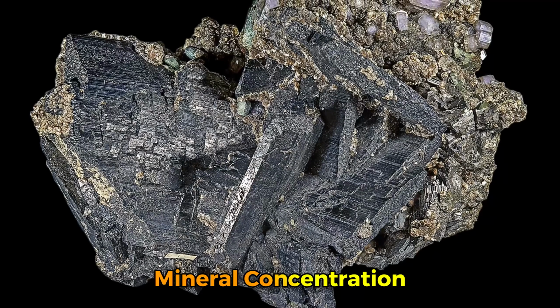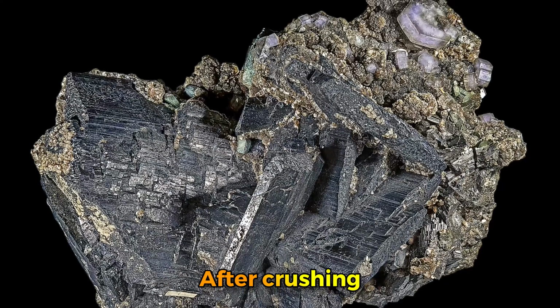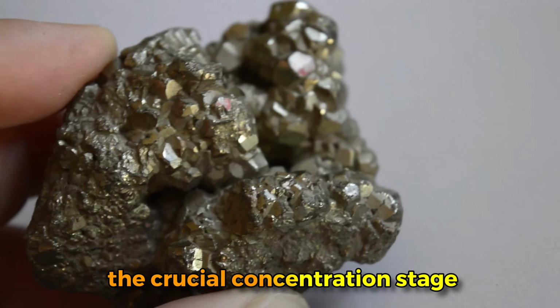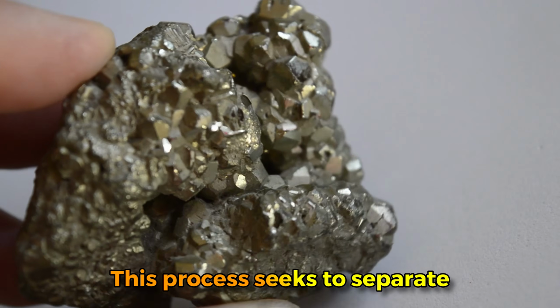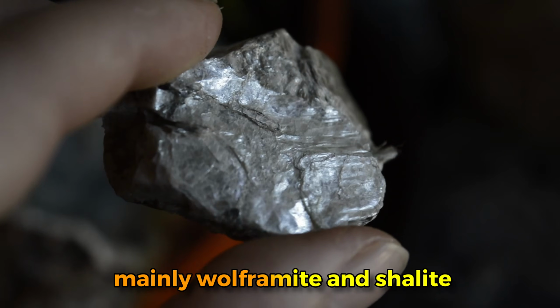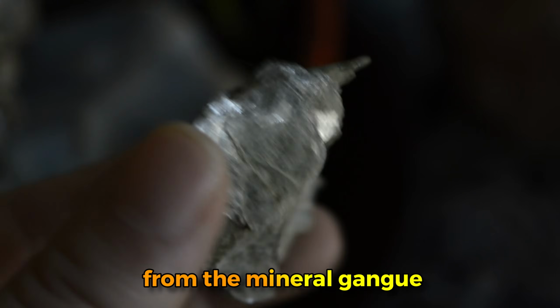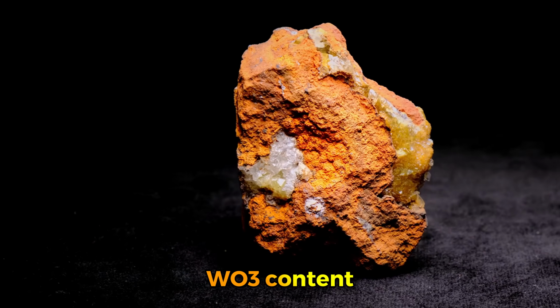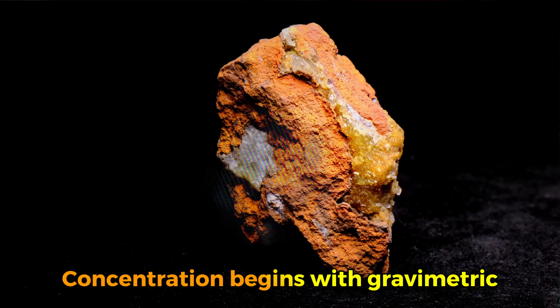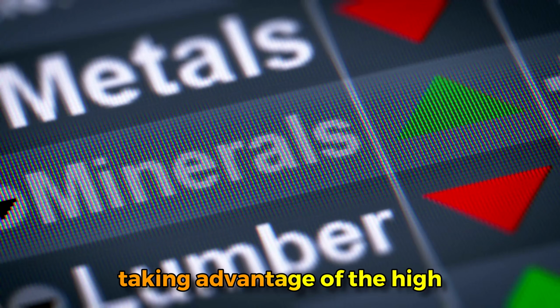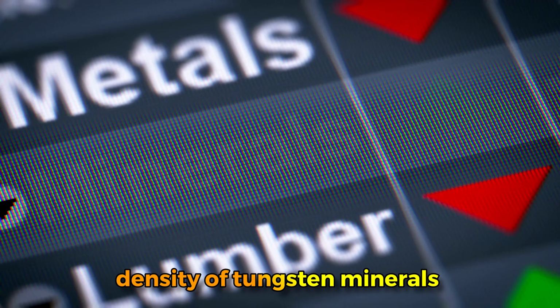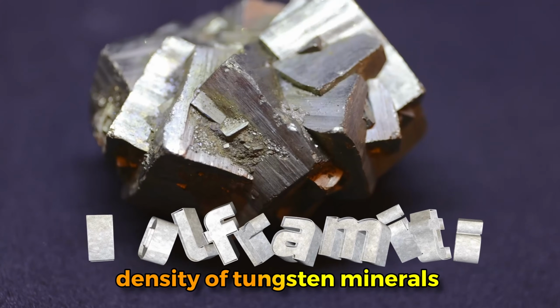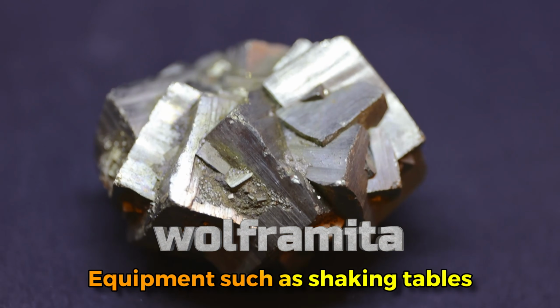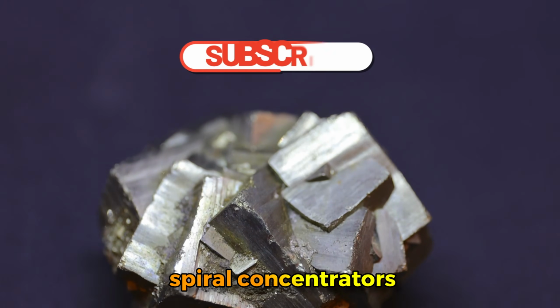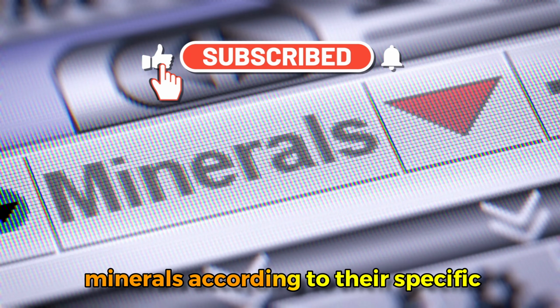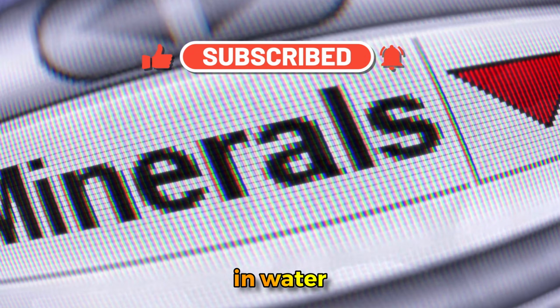Step 4. Mineral concentration. After crushing, the pulverized mineral enters the crucial concentration stage. This process seeks to separate the valuable tungsten minerals, mainly Wolframite and Scheelite, from the mineral gangue, significantly increasing the WO3 content. Concentration begins with gravimetric methods, taking advantage of the high density of tungsten minerals, 7.1 to 7.5 g/cm³. Equipment such as shaking tables, spiral concentrators, and jigs are used to separate minerals according to their specific weight during their movement in water.